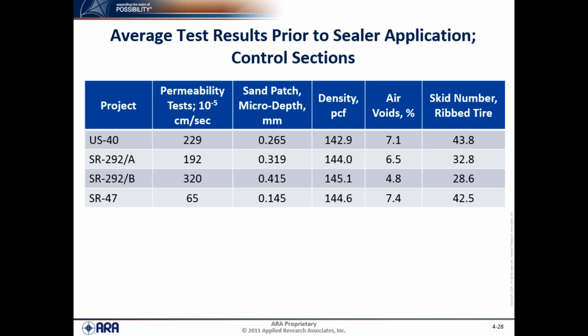Sand patch, again, and what's shown here should be macro, not micro depth, macro depth, MACRO, in terms of millimeters. The State Route 47 had the lowest, 0.145, and again, State Route 292B had the highest macro depth measurement.